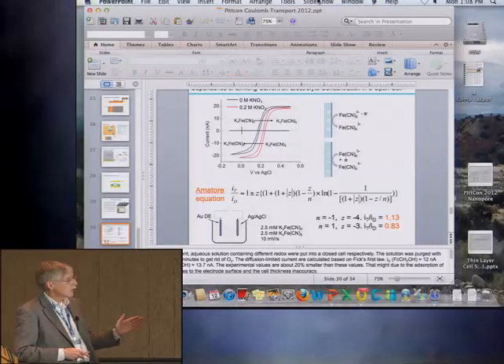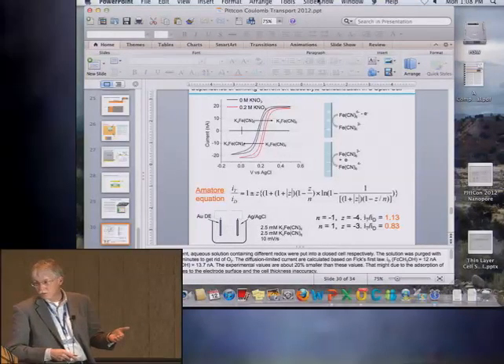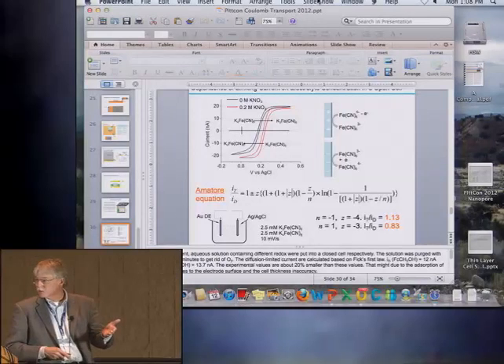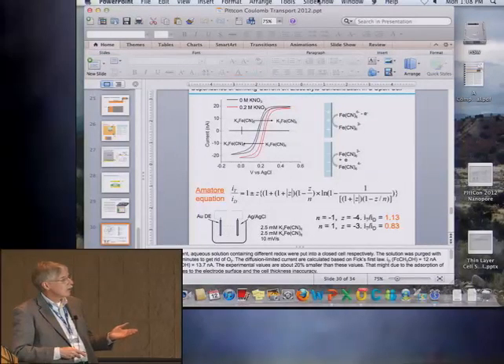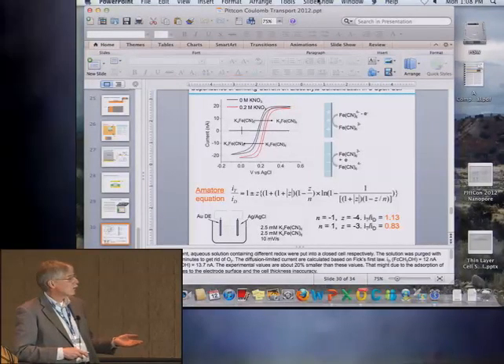Forget about that. But there's a change in the limiting current here. For the oxidation of ferrocyanide, there's a slight increase. That's because when you oxidize ferrocyanide and go from -4 to -3, that's equivalent to making a positive charge at the electrode surface in the solution, and that sucks in, through migration, the ferrocyanide reactant at a higher rate. Likewise, when you're reducing, you go from -3 to -4, creating an extra negative charge in solution, and that acts to repel the incoming reactant, so it slows it down.